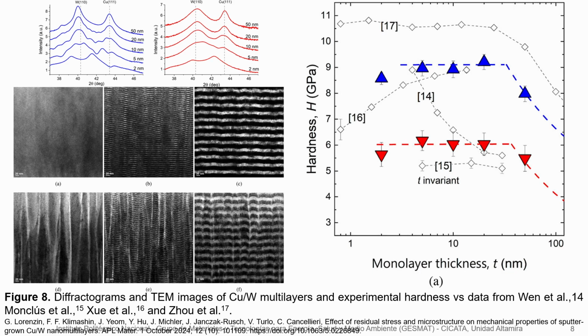In the literature, there is a discrepancy in the mechanical properties reported for these multilayer systems. Multilayer systems with individual layers of varying thicknesses exhibit different hardness according to different authors. And since there is no standardization of the fabrication process, there is high variability in the reported properties, even in systems with the same layer thickness.